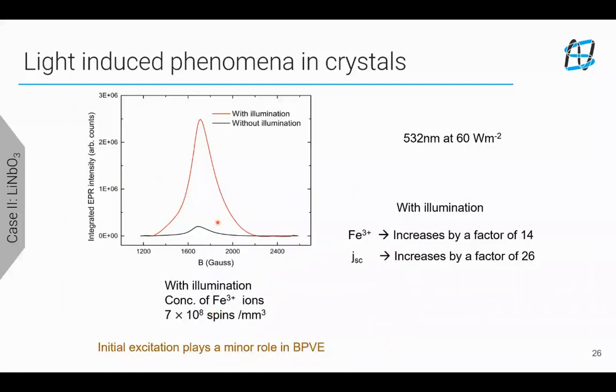And since it has a 3m symmetry, whenever you rotate the magnetic field, you can see the spin of the Fe3+. So what we did was we took that and we integrated the peak of the Fe3+ spins. And this is called the spin counting procedure. So we counted the spins with illumination and without illumination.